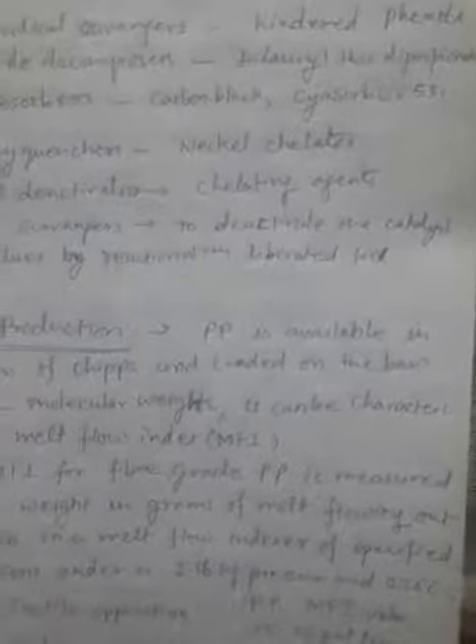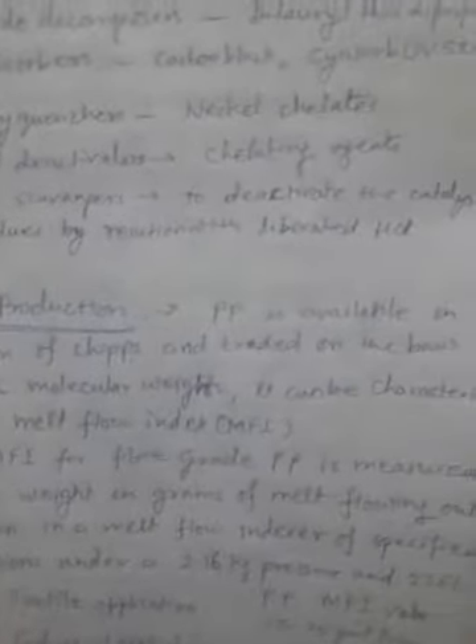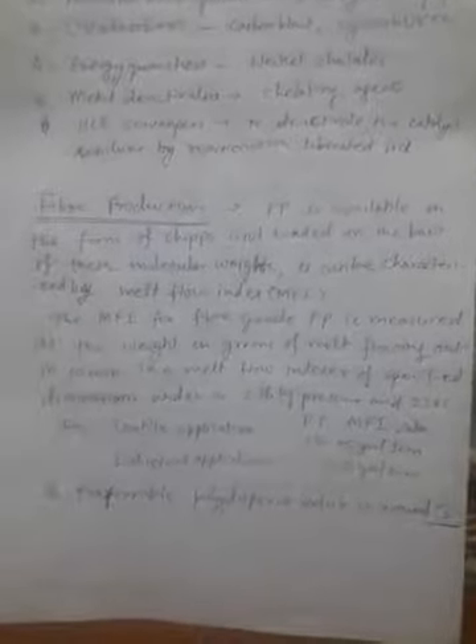scavengers. That means any material which is rich in HCl, which is liberated by decomposition, and that liberation of HCl molecules may deactivate the catalyst residues if still present in the polymer system, or you can say in the polymer molten mass. So to deactivate the catalyst residue, HCl scavengers can be added.